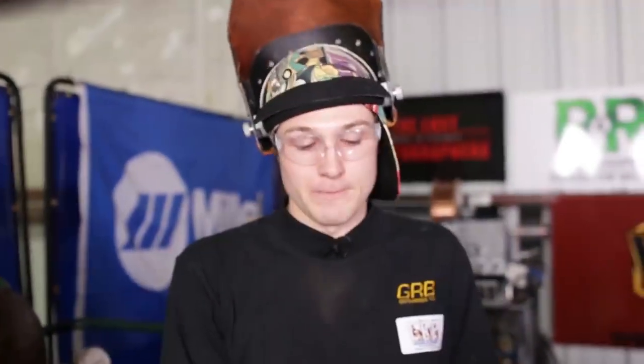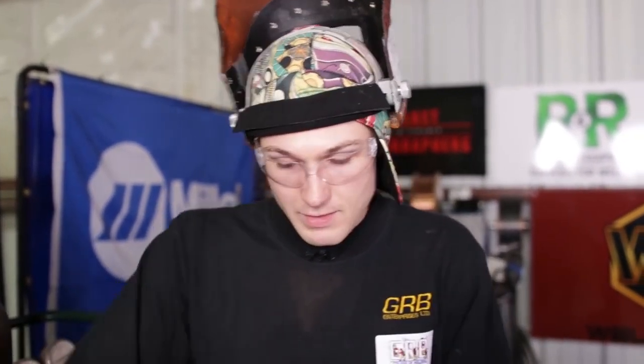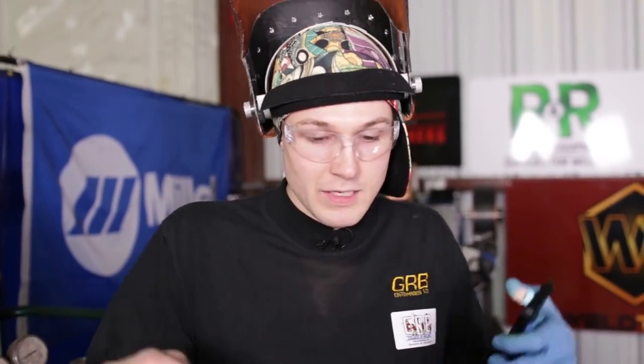a lot of guys will figure they have to weld cold. But when you weld cold, it takes a long time for the weld puddle to break down the parent material, or the previous pass you're welding on, and get the puddle to move around. Essentially, on that little speck you're welding, you're overheating the material trying to get that puddle to move. A lot of times it's better to increase the welding current so your weld puddle immediately washes outwards and you can start traveling from A to B, rather than being stuck in one spot on very low current, not going anywhere but expelling a lot of energy into the material in one spot.